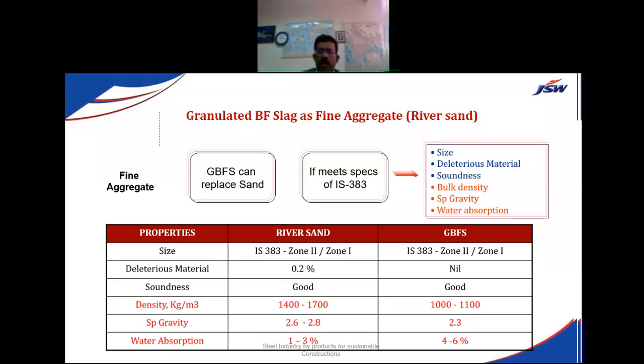River sand is there, and also GBFS, the original material. It was not meeting the exact requirement in terms of specific gravity and density, because river sand density was 1400 to 1700 kg per meter cube, and this slag was giving 1000 to 1100 kg per meter cube density. Specific gravity was also less, and water absorption was a bit more compared to river sand.